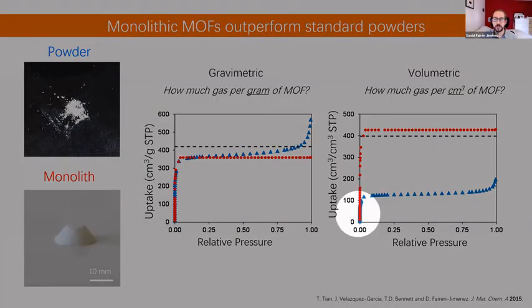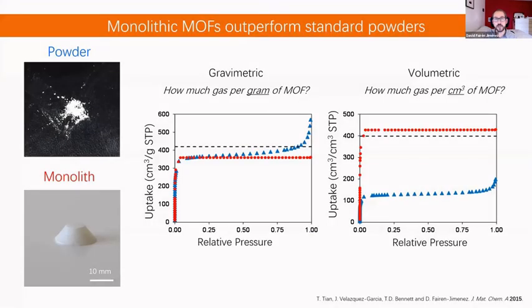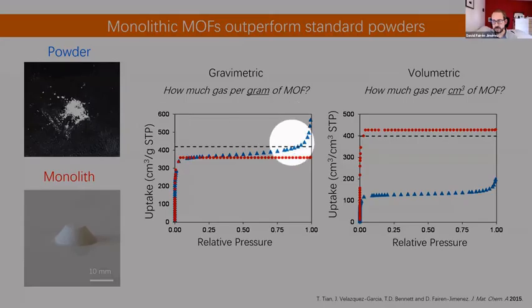The big difference is when we go to the volumetric capacity of the monolith. There is 3 or 4 times higher absorption capacity in the monolithic structure, just because in the powder we have a lot of dead volume between the particles that we cannot really use to absorb a gas. This is why we have a little bit of tail here going up, but this is something we will never exploit. And one of the first examples that we published in 2018 was for natural gas storage.